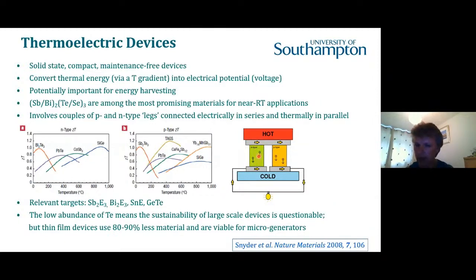So this sort of arrangement here, where this would be one thermoelectric material, the N-type material, and the P-type material on the other side. And by connecting these electrically in series and thermally in parallel with this temperature gradient, a hot side and a cold side, we can turn that temperature gradient into electricity. And of course, that's the means of creating the power.